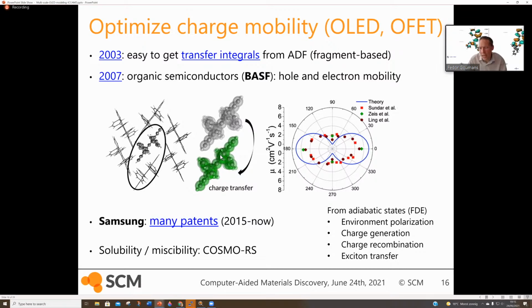And so one year later from the paper that I mentioned, they did another paper where they used a Monte Carlo based approach, basin hopping, to deposit these molecules and then take pairs of molecules out of this disordered crystal and calculate the mobility, calculate the transfer integrals, do some integration over those mobilities to get the total mobility in the different directions.